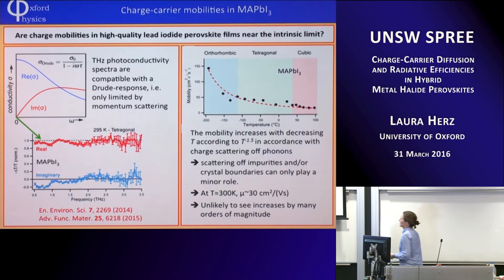We also see something else resembling gallium arsenide: as we reduce the temperature, mobility goes up by about a factor of 10. That is typical of a system where mobility is limited only by scattering with the lattice — with phonons. In more disordered systems you see the opposite: impurity scattering dominates, or in molecular systems you need some activation energy to move charges. Again it looks exactly like gallium arsenide, and it suggests that at room temperature we get about 30 cm²/Vs — which may not be brilliant compared to gallium arsenide, but we're already in a regime not limited by crystalline boundaries or defects.